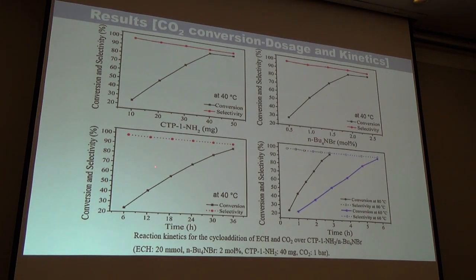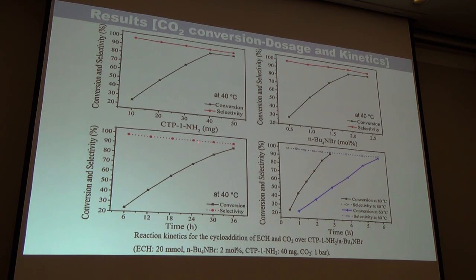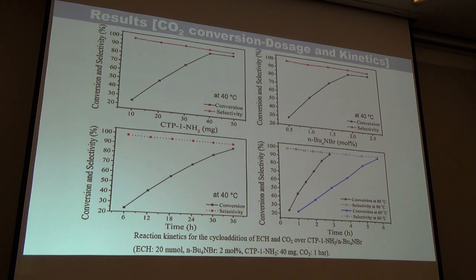So the catalyst loading was tested from 10 milligram to 50 milligram. As you can see, the conversion of epoxide increased linearly until the 40 milligram loading, and then it became saturated. So the optimum amount is 40 milligram. Meantime,